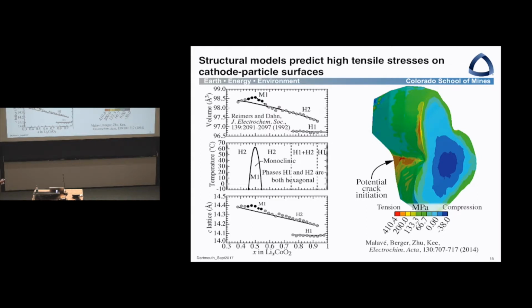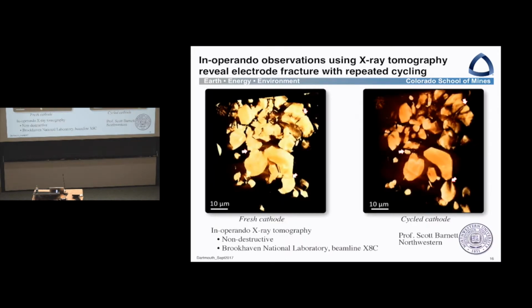So what happens, in fact, is that in crack-like features on this cobalt oxide, you have stress risers near that crack, and they tend to be tensile. And so as you intercalate, that tends to work cracks and open them, which is not what you want to happen. I'm showing here an image that we did together with Scott Barnett at Northwestern, where in this case it's not a FIB-SEM, but X-ray tomography, where we put a cathode and did X-ray tomography and looked at places that were initially quite well connected. Then we cycled the battery, not many times, like 10 times, and what you can see is places that were intact are now floating free.